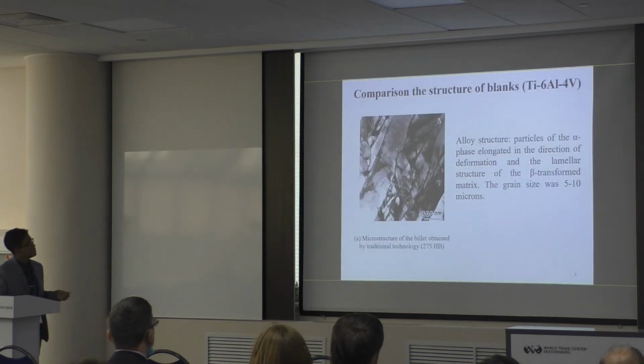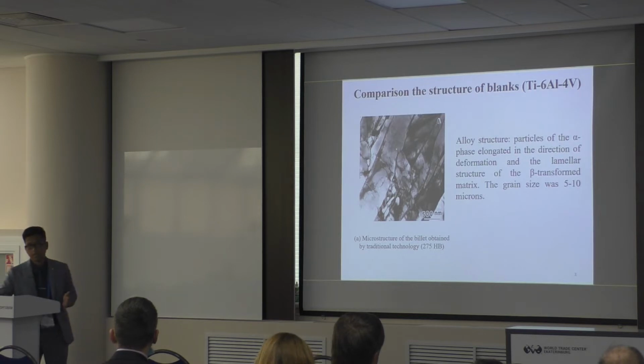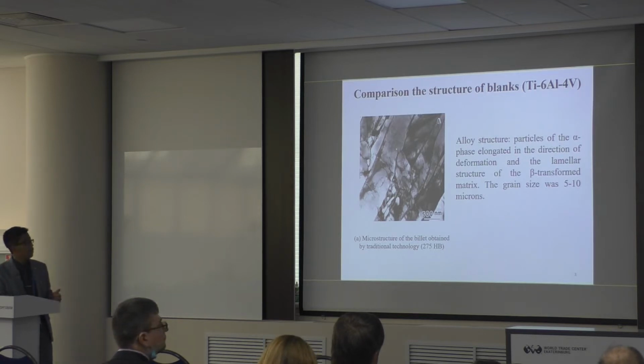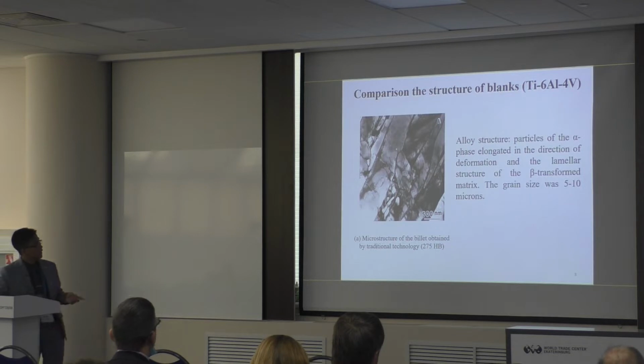And in the slide, we can see figure A, the workpiece obtained by traditional technology, forged, which underwent incomplete annealing at a temperature of 680 degrees Celsius for an hour with cooling in the air. And the hardness of the material is 275 HB.